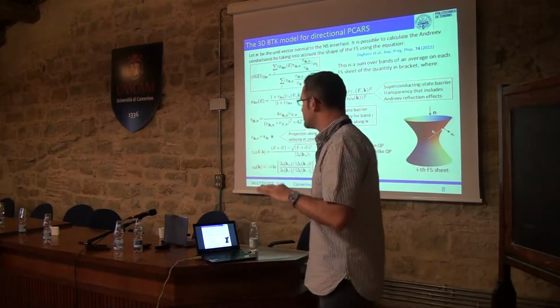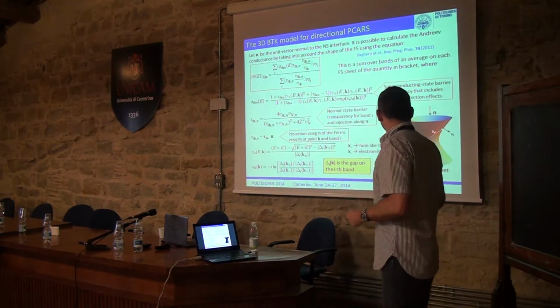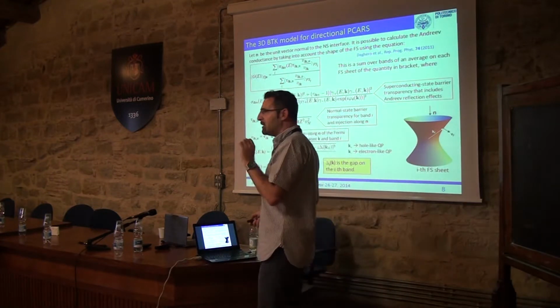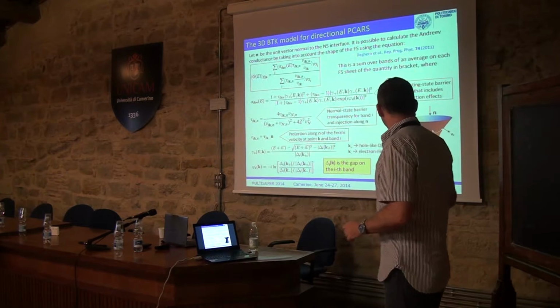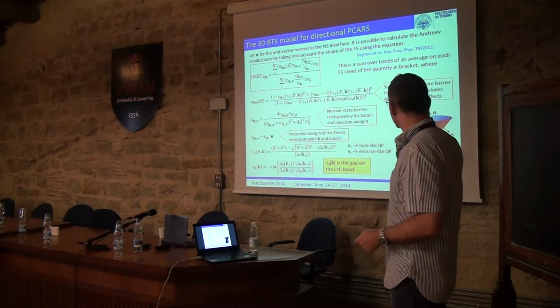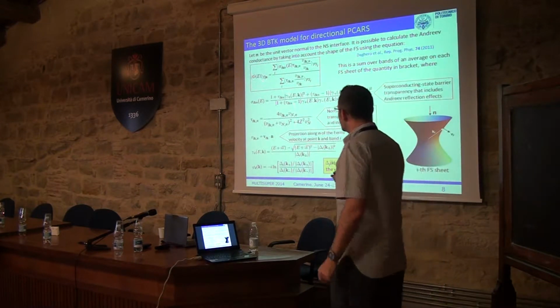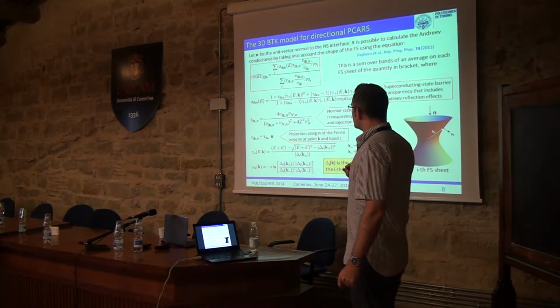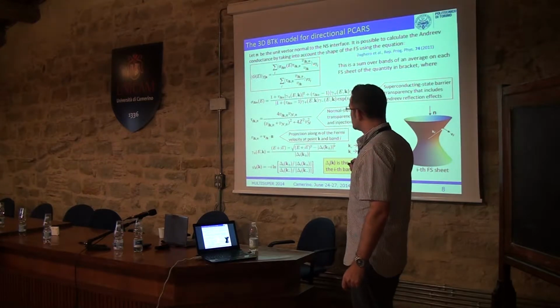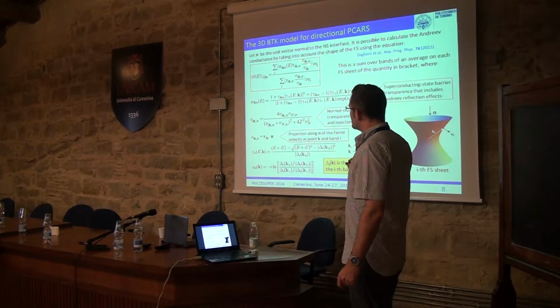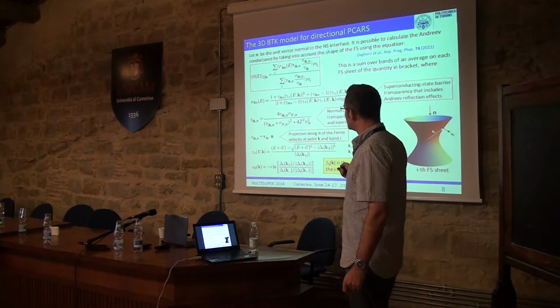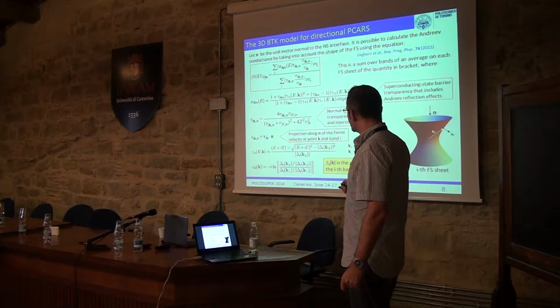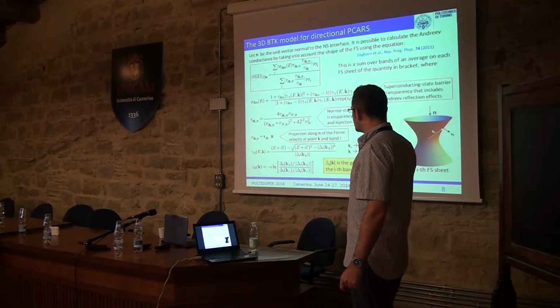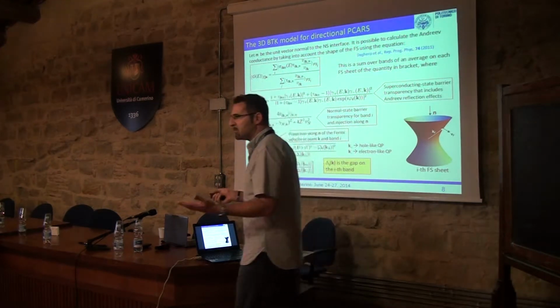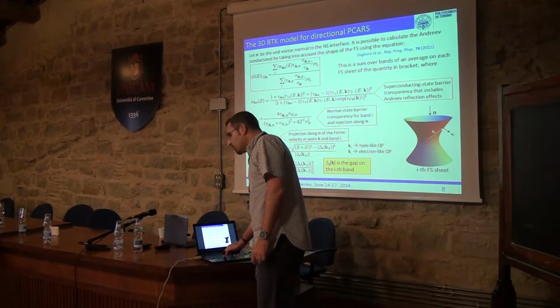Don't be scared. These are the last formulas I will show. The 3D BTK model is intrinsically multiband, because you can have as many bands as you want. Suppose this is the Fermi surface sheet, then this is the direction of current injection, in this case vertical. Then the normalized conductance is expressed by this ratio. Here you have a sum over the sheets of the Fermi surface, and this is an average over the ith Fermi surface sheet. These quantities contain only information about the shape of the Fermi surface, and this quantity contains, through these functions here, the information about the order parameter, that can have in principle any dependence on the direction. So this is the model we are going to use later.